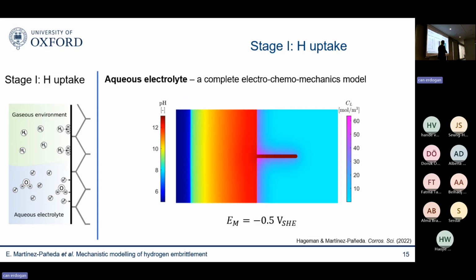This is a typical quantity. You solve, for example, the pH inside of the electrolyte. You can see that it changes quite dramatically from inside the crack to outside the crack, as you would expect. And then you can predict the hydrogen uptake as a function of time, as a function of your material, as a function of the fluid flow, as a function of applied potential, and so on. This is just a representative result. But I guess the end point is that for whatever environment you have, you're able to quantify hydrogen uptake.